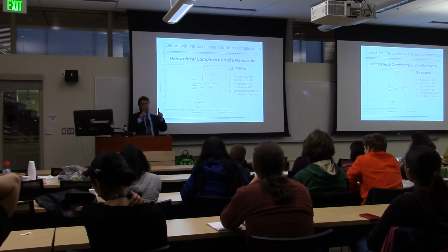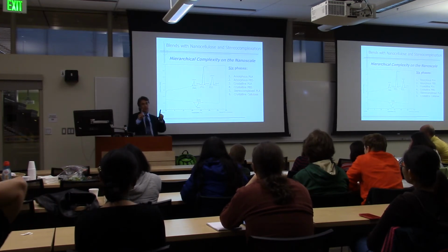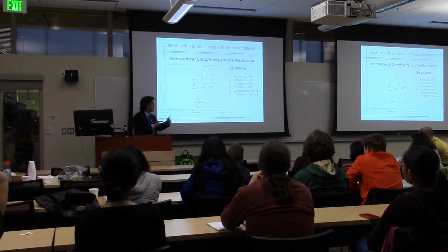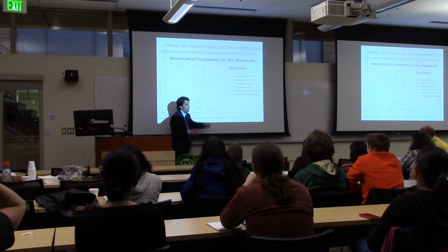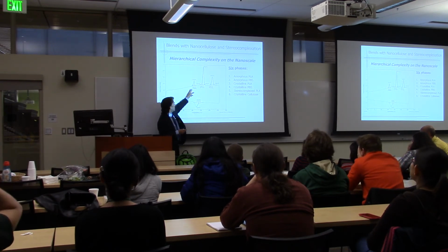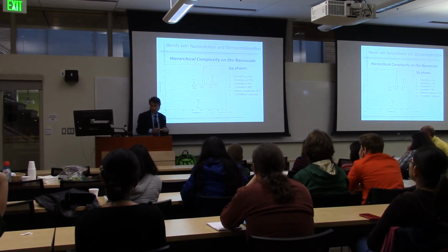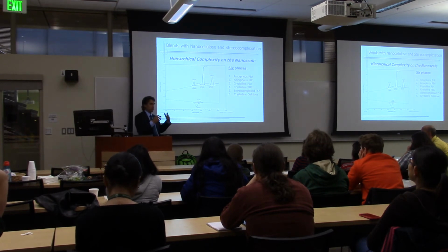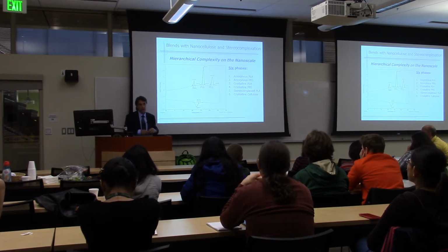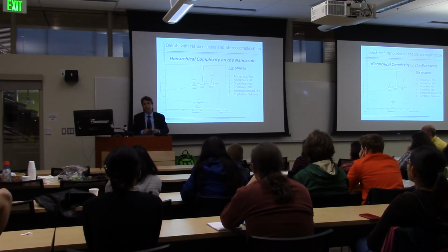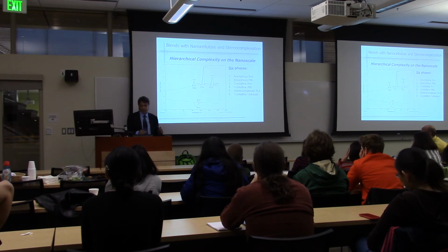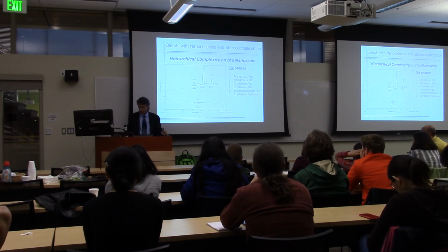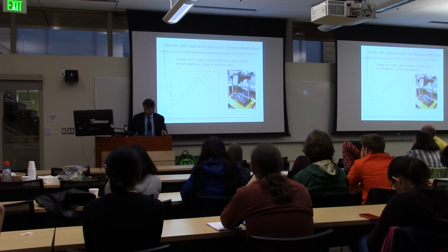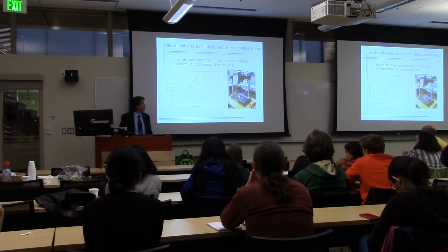We have the two homopolymers of PLA, so there's a melting temperature at 180 degrees, but they stereocomplex, so there's a melting peak at 230 degrees as well. And now we've put in PBS as well, so there's a melting peak down at 105 degrees. If you think about making this witch's brew, we have 6 separate phases present now in our nanocomposite material. We're still working to sort that all out: what does the organization and the structure really look like? But in the meantime, we use the usual types of tools.